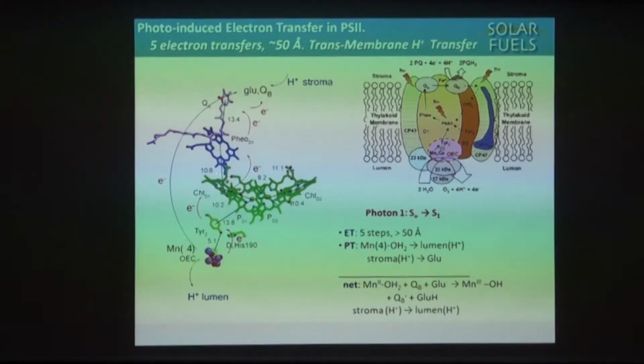It makes a singlet excited state. It undergoes rapid electron transfer, first to a pheophytin, the porphyrin derivative, and then it undergoes further oxidation to a quinone, where quinone gets reduced to semiquinone. That drives a proton into the membrane from the top. Following that, the oxidized site electron transfer occurs. That leaves behind a porphyrin radical cation, this P680+.